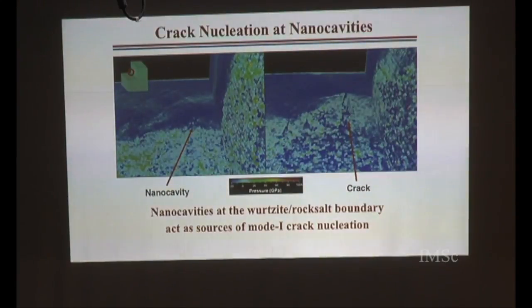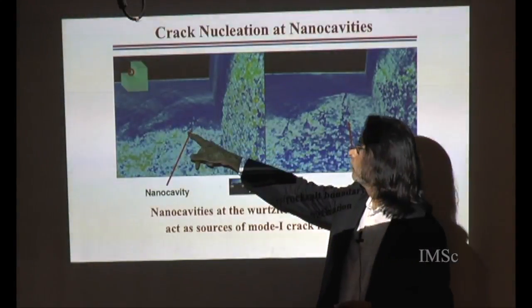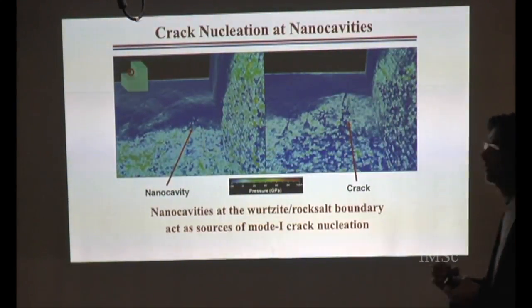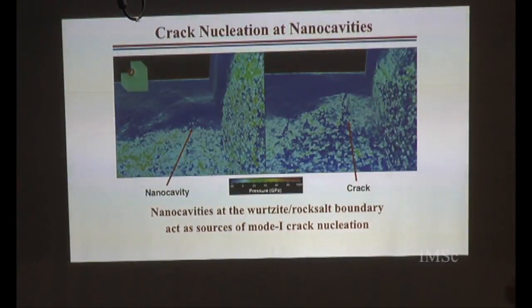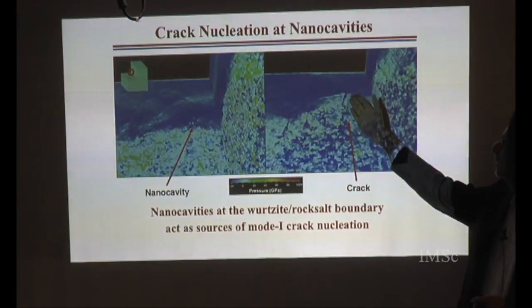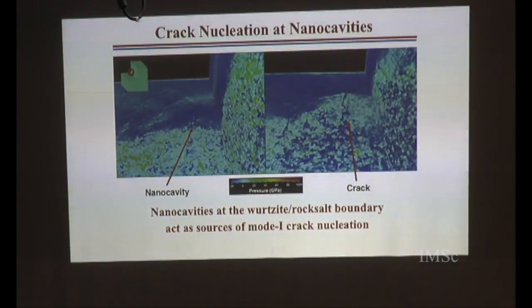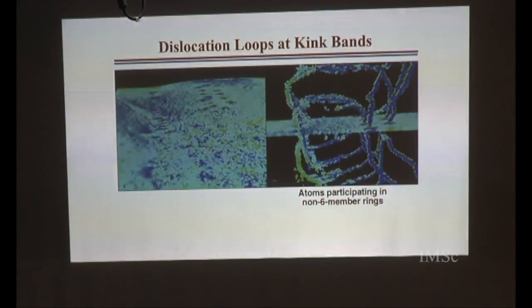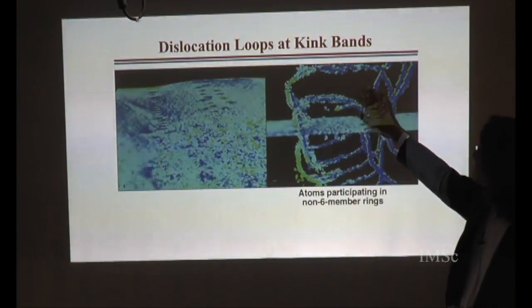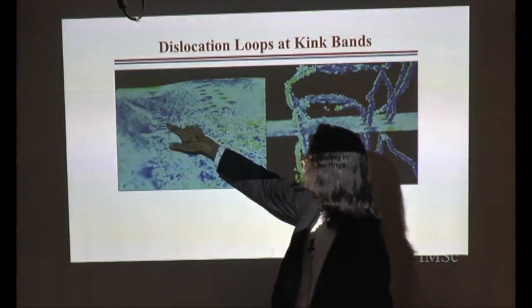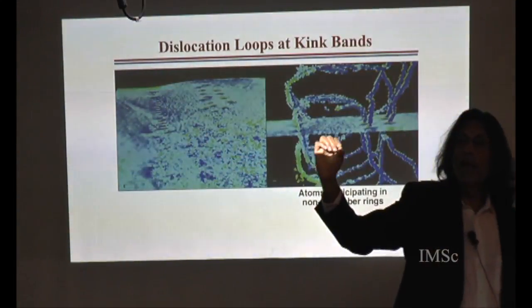The stress wave reflected from the back end of the sample comes, and when it hits this interface between rock salt and Wurtzite, it begins to nucleate defects. The kind of defects we see over there are nanovoids, for example, over here at the boundary, and then these nanovoids grow, they coalesce, and then you begin to form cracks also, and this is happening at the interface of the structural phase transformation. In addition, what we see in the system are dislocation loops, and these are dislocations running through the system, forming a sort of a kink band, okay?